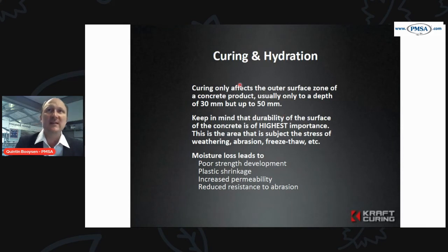Curing only really affects the outer surface zone of the concrete. So typically about 30 to 50 millimeters of that concrete, that outer skin. So the inside of the concrete is normally kind of well cured because the water doesn't all escape and it's well wrapped around the casing of the outer skin.